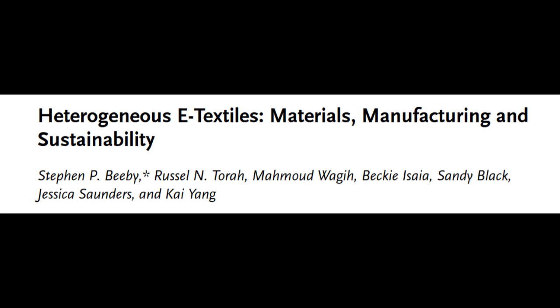The source notes, though, that applying these very thin film devices like solar cells directly onto a typically rough, textured fabric surface often requires putting down a smooth planarization layer first. To make it flat. Right. And some of the processes involved, especially for certain types of solar cells, might require high temperatures, like 400 degrees Celsius, which could damage many common textile fibers like cotton or polyester. Though lower temperature processes, maybe around 150 Celsius for organic solar cells on polycotton, are also being developed.